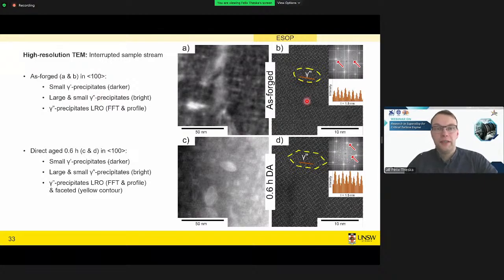Nonetheless, we can do a fast Fourier transform. That's this top inset, and we do see some superlattice peaks, which show us the presence of precipitates, as well as the brightness profile shows us some ordering too. The situation is quite similar after 0.6 hours direct aging, except that these superlattice spots and the ordering in the profile become stronger.